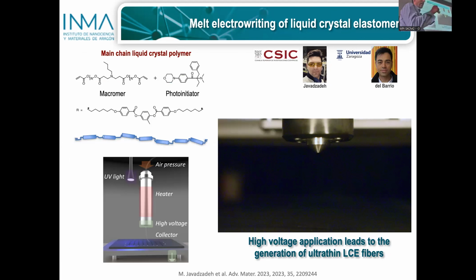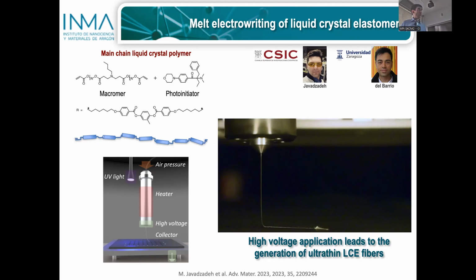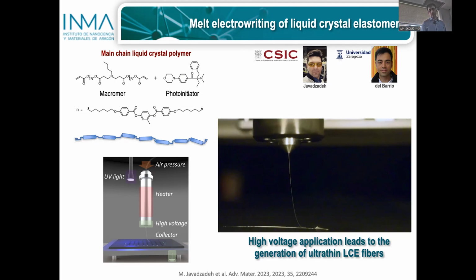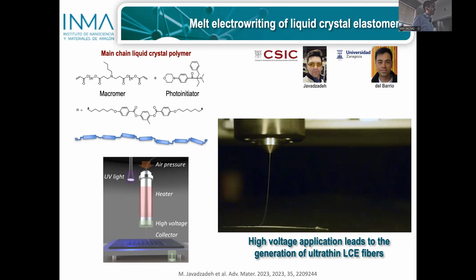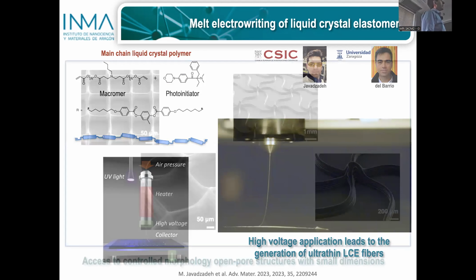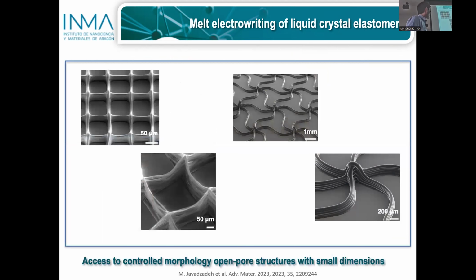If you have no voltage between the nozzle and the substrate, nothing happens. The material is not able to flow. But as soon as you apply a high voltage of some kilovolts, then the material appears, and it gets charged, and it's drawn into a fiber, and at the end we get an extremely thin fiber that we can start to move in order to generate structures.